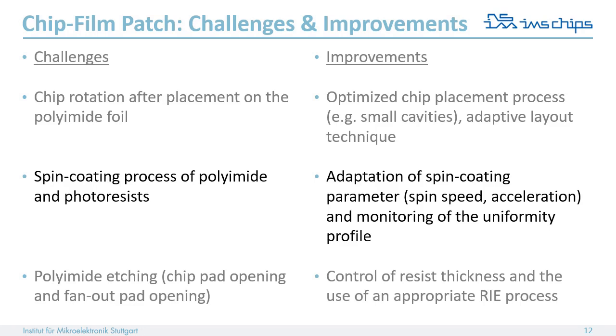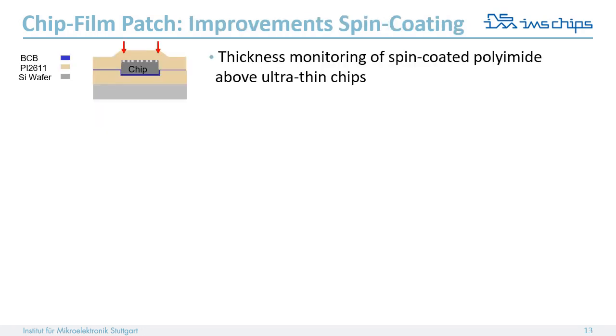Since polyimide shows a different spin coating behavior due to its higher viscosity, this leads to more surface inhomogeneity on the substrate. The coating process was then fine-tuned for each material by changing the spin speed, the acceleration, and the intermediate soft bake. Furthermore, we are able to monitor the polyimide uniformity profile above the embedded chips, which we'll discuss on the next slide.